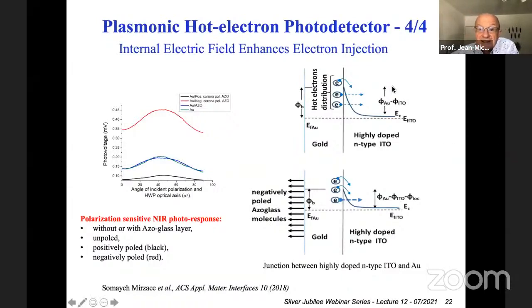So this is exactly the situation that we have. And by orienting the dipoles, what we do is just change the energy of the vacuum into which the gold is. That reduces the tunneling barrier and increases the probability of the electron to go into the ITO and be detected by our photodetector. The polarization sensitivity is a little bit different.